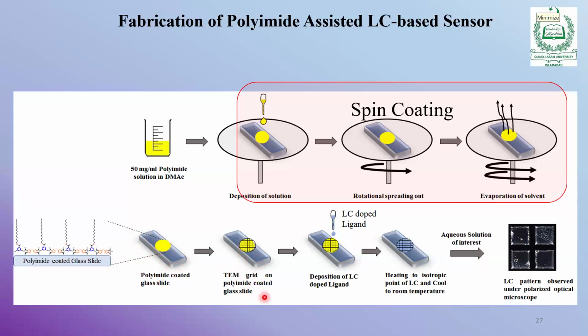Then we put a TEM grid on the slide, we deposit a liquid crystal which is doped with a ligand, and then we heat the liquid crystal above its liquid crystal to isotropic transition. In the isotropic state, liquid crystal molecules are randomly dispersed. So we anneal, we heat it to a higher temperature in the isotropic phase, then we cool it down to room temperature. After heating, when we cool down, the liquid crystals try to align themselves with the grid. And what we see, if they are aligned homeotropically, is some liquid crystal pattern under the polarized optical microscope.